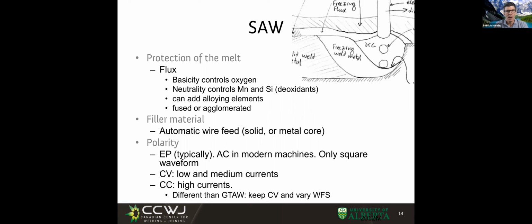The fluxes are powders, and there are two large types of these powders. One type is called fused. That is pretty much crushed glass. And this is the oldest type of flux. And as you know, when glass gets hot, it melts down, and this molten glass creates an insulation between the molten metal and the atmosphere. And this molten glass is essentially inert. It doesn't react with the melt.